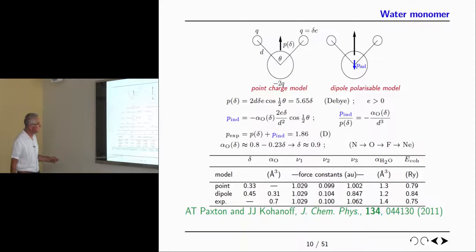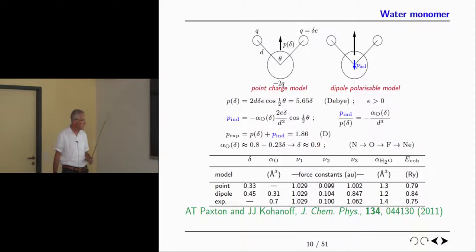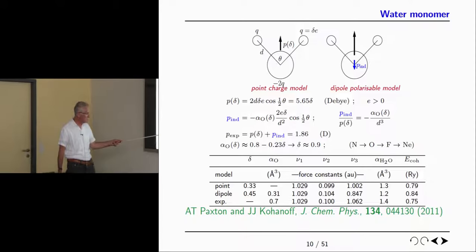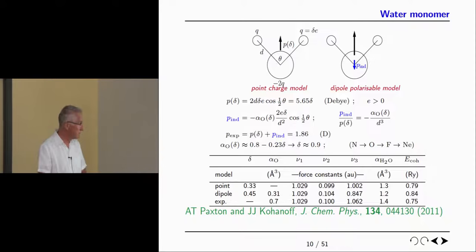And you can calculate the dipole moment just from geometry. It's just a function of the amount of charge delta. So we have this Hubbard U. We can turn this big Hubbard U knob, which is one of our parameters, in order to obtain a certain charge transfer, if you like. The dipole moment generated by these three point charges is simply given by this formula in electrostatics, and it depends on the quantity delta. If we know the target dipole moment, which in the water molecule is 1.86 Debye, then we can simply tune our U in a point charge model to produce a water molecule. And that's the data on the first line here, some results of simulations on a single water molecule.